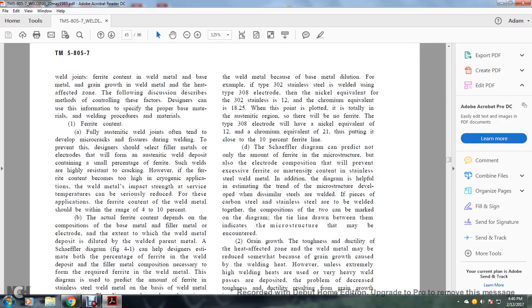The Schaeffler diagram can predict not only the amount of ferrite in the microstructure, but also the electrode composition that will prevent excessive ferrite or martensite content in the stainless steel weld metal. In addition, the diagram is helpful in estimating the microstructure developed when dissimilar steels are welded. If a piece of carbon steel and stainless steel are to be welded together, the compositions of the two can be marked on the diagram. The tie line drawn between them indicates the microstructure that may be encountered.